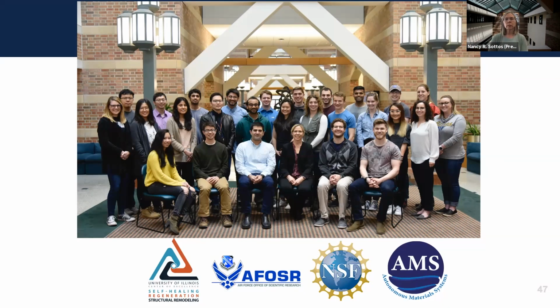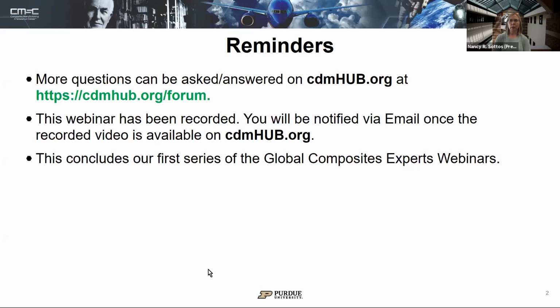In terms of surface functionalization, we've been talking to some different groups. There's a lot of work going on with DCPD composites in the U.S. Army because of their toughness and resistance to projectiles. And there's been a lot of efforts there on the glass DCPD interface. There's also quite a bit of proprietary work on glass DCPD interfaces. And then a few groups, some in Australia, have been working on the carbon fiber interface. I just showed the three strategies that we've looked at so far for surface functionalization. And that's about where we are now.